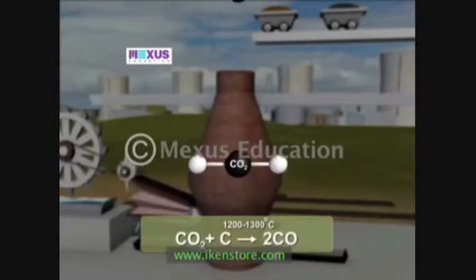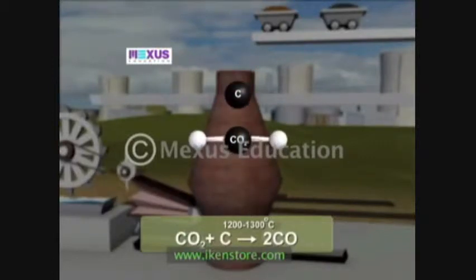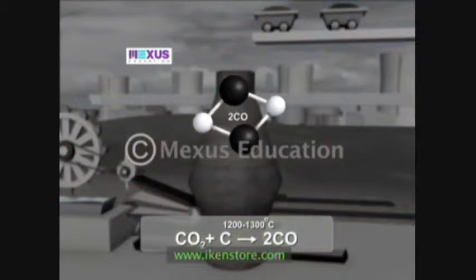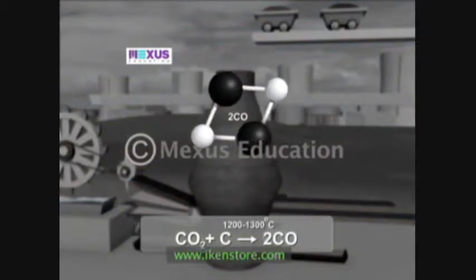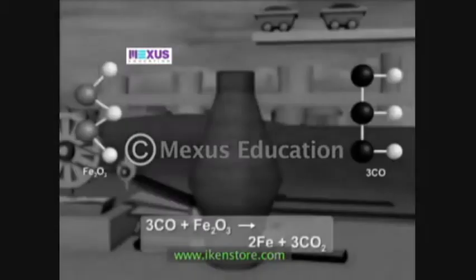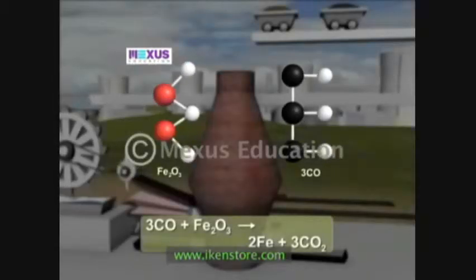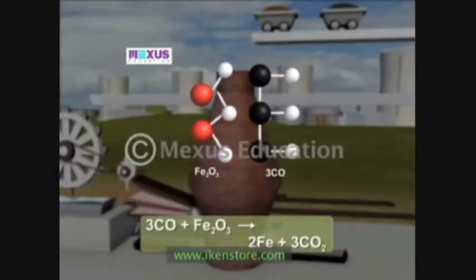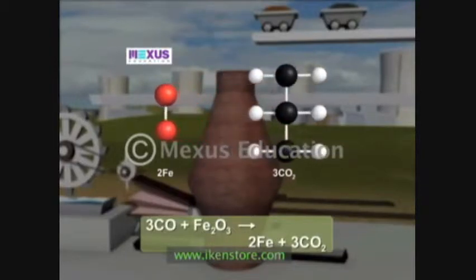Carbon dioxide oxidizes coke to form carbon monoxide at a high temperature of 1200 to 1300 degrees Celsius. The carbon monoxide then reduces the ore to iron, taking on oxygen and reverting to carbon dioxide.